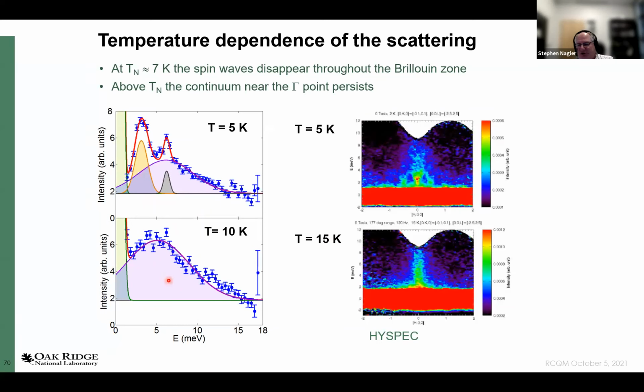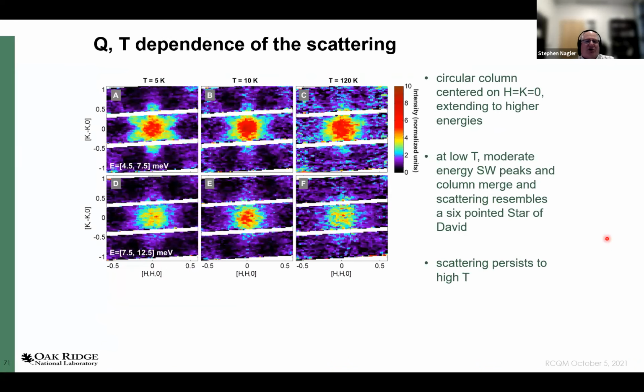So you can see that here in a constant Q scan and here in one of these energy momentum scans. So here's something showing more broadly the Q and temperature dependence of the scattering, showing this kind of large continuum.